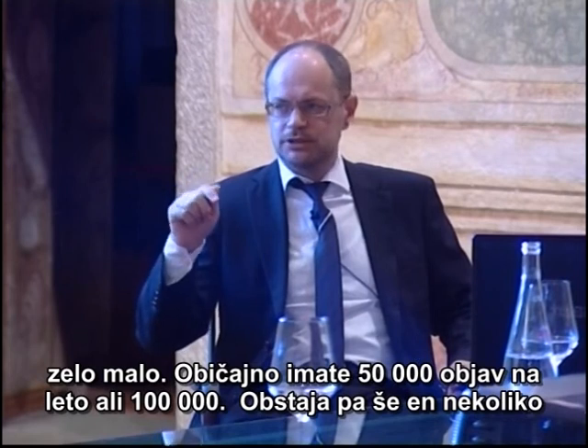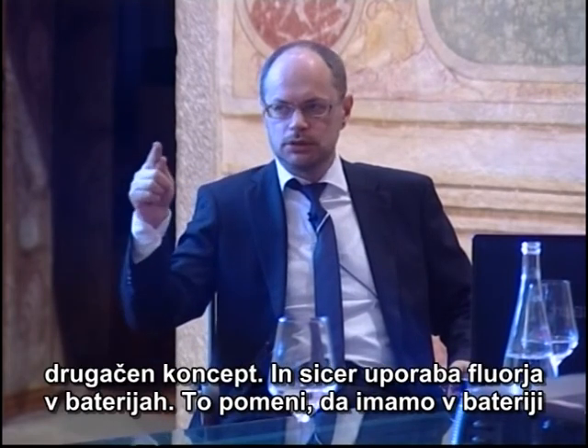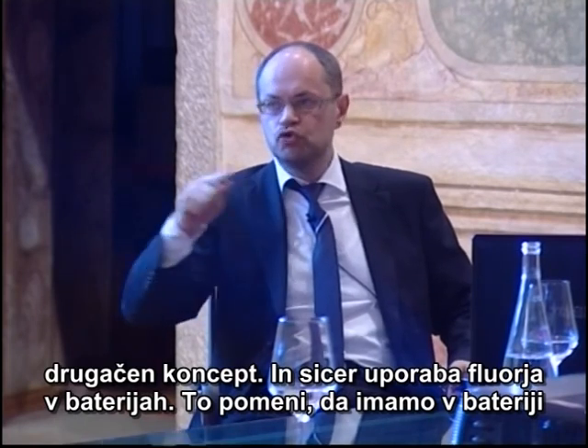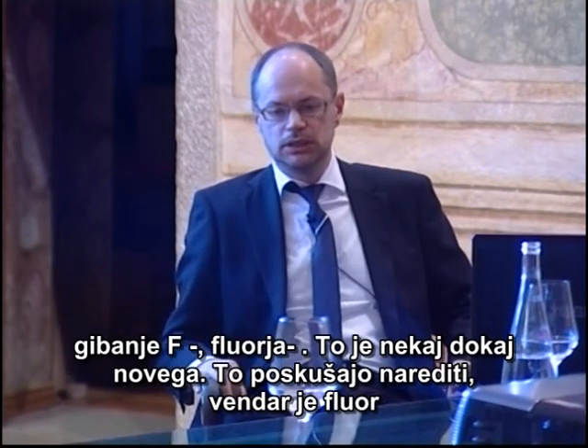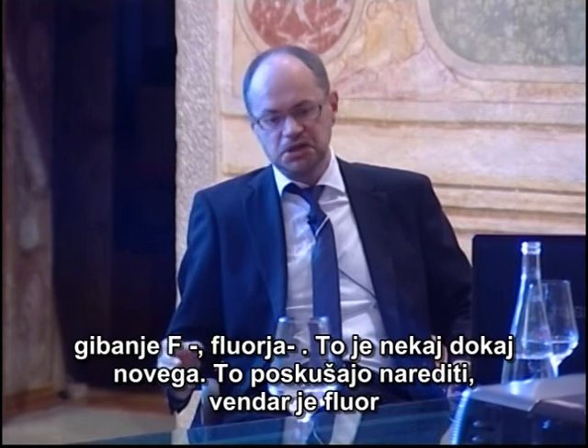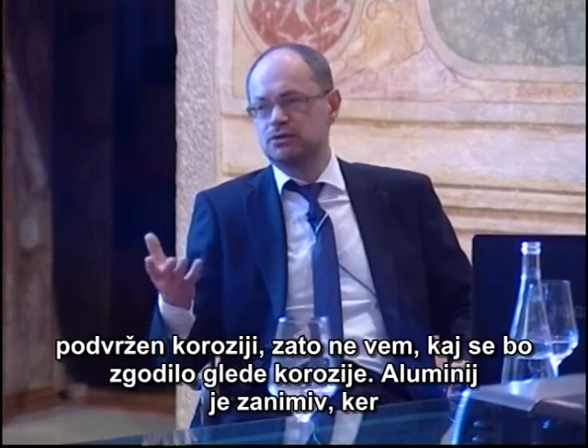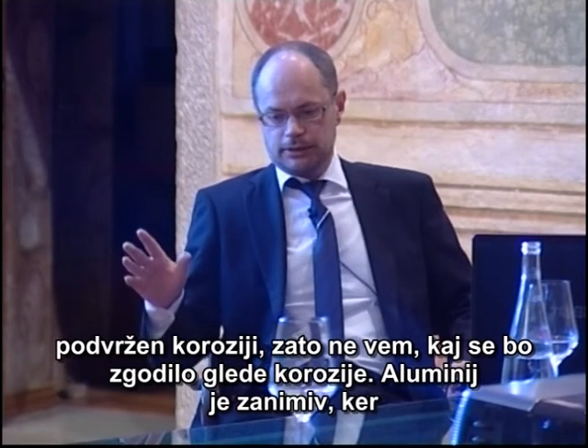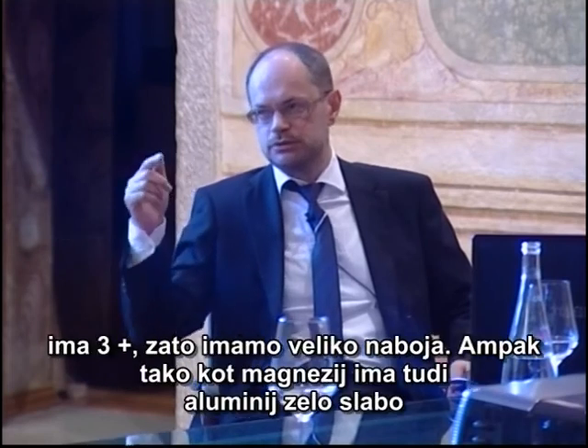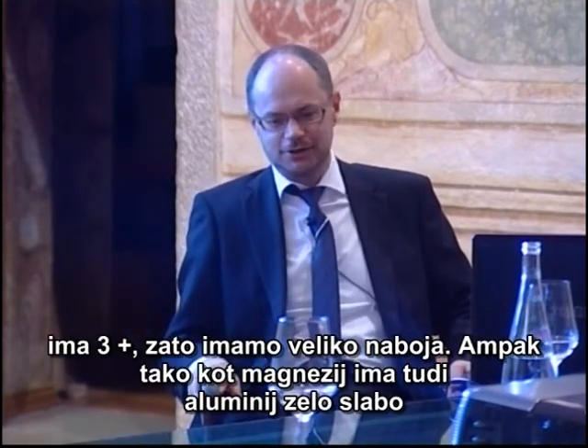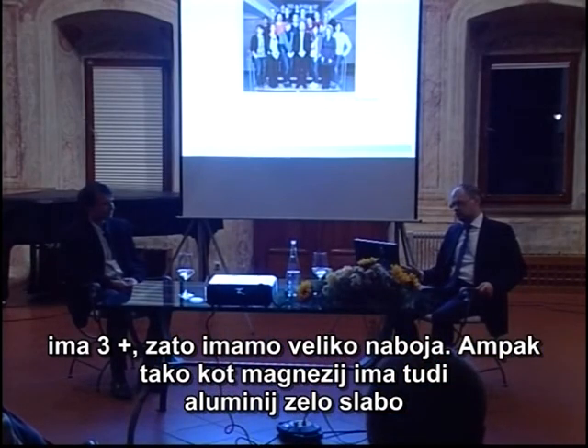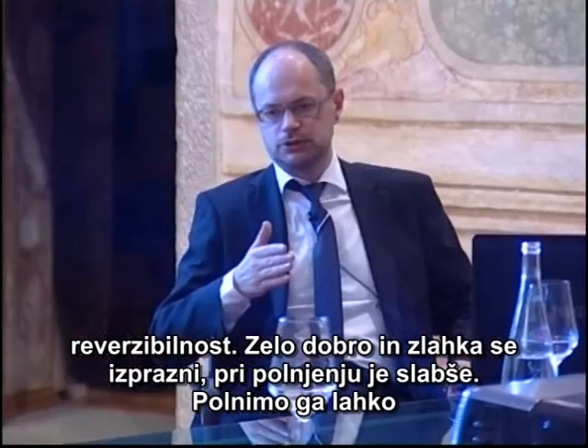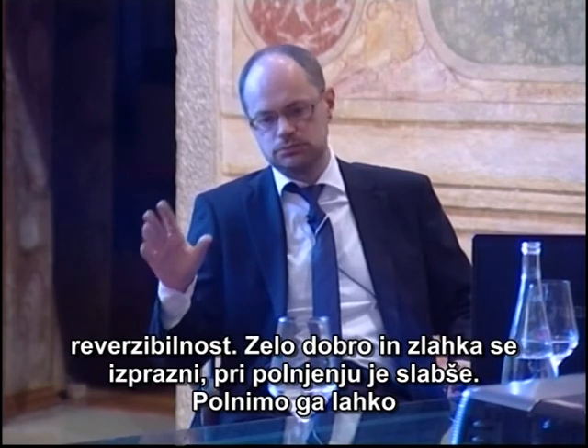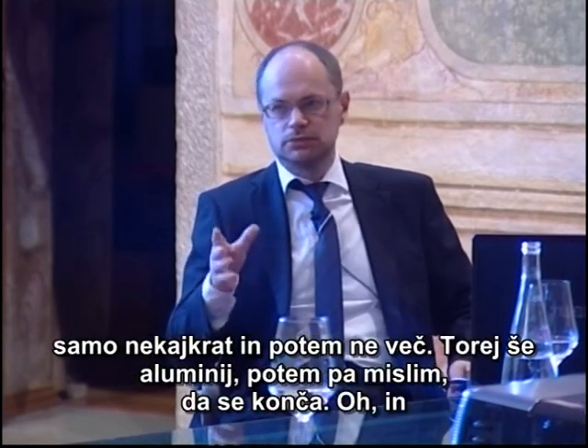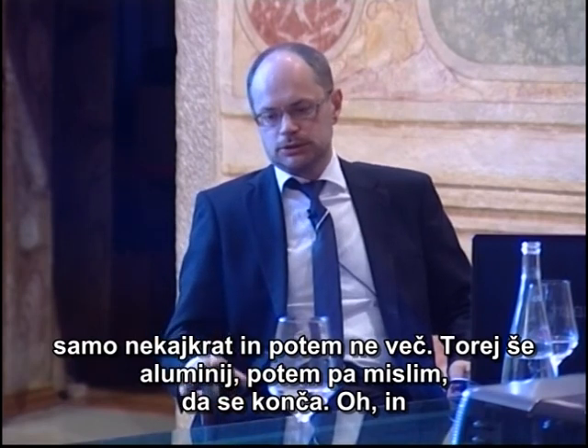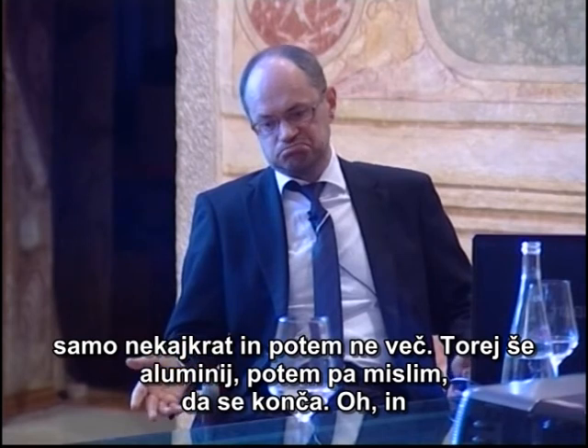Then there is another concept which is a little bit different. For example, a fluorine battery. This means you have movement of F minus, fluorine minus. This is something which is quite new. They are trying to do it, but fluorine usually is related to corrosion, so I don't know what happens with corrosion here. Then aluminum is interesting because it has 3+, so you have a lot of charge, like magnesium. Aluminum has very poor reversibility, so you can discharge relatively easily, at least in the lab, but when you charge, you have only a couple of charges and then it stops. So aluminum is another, and that's it, I think.